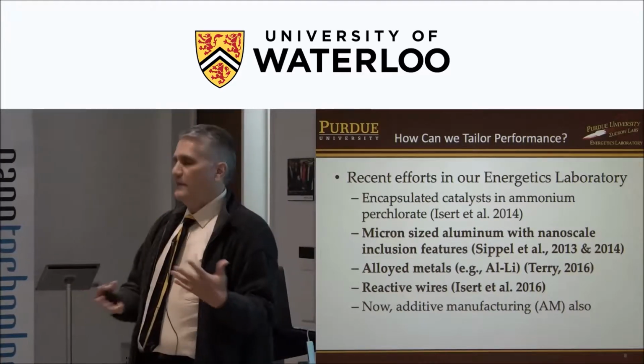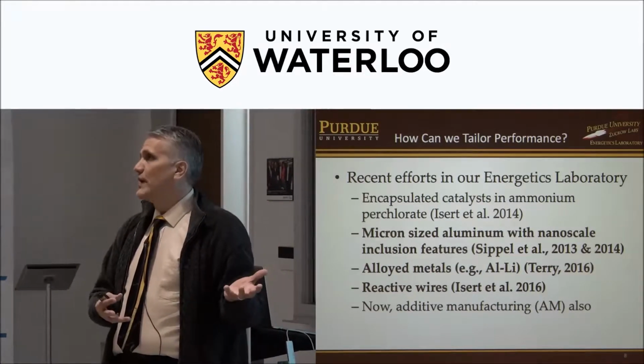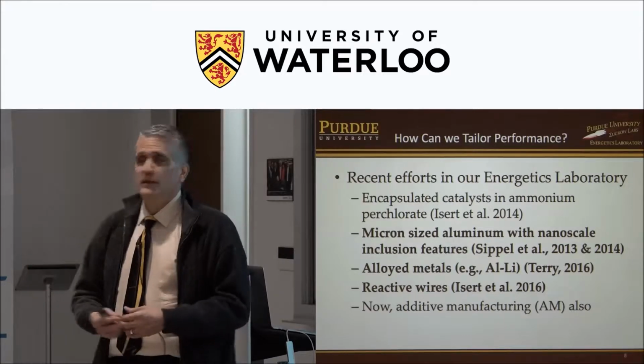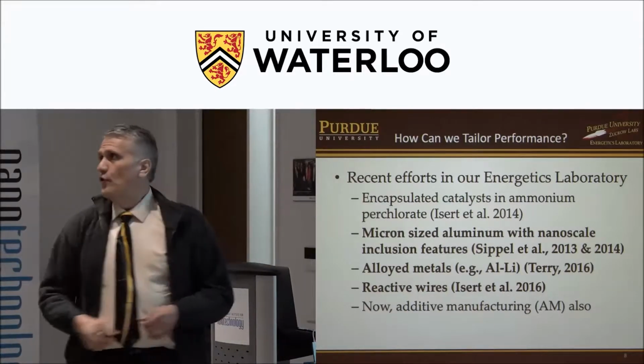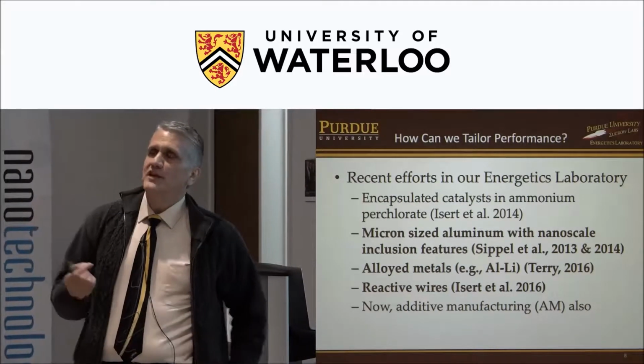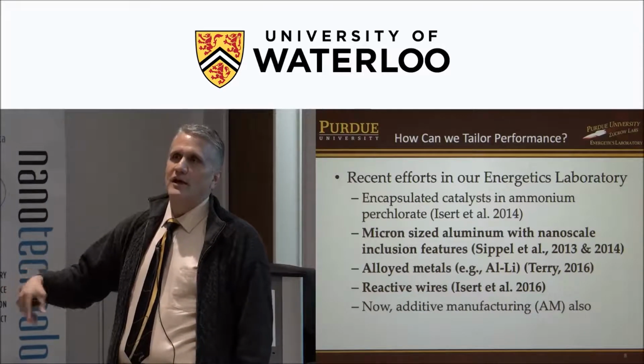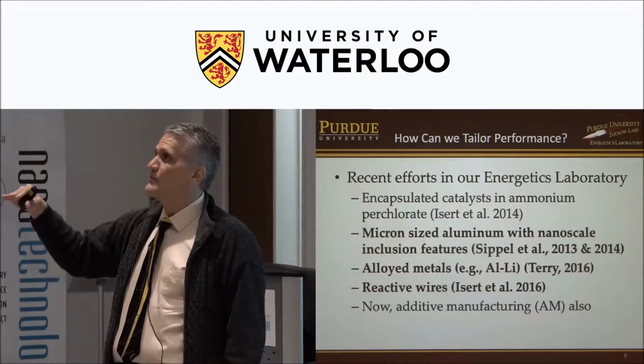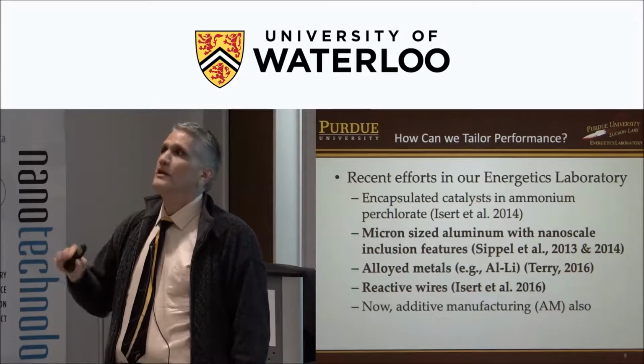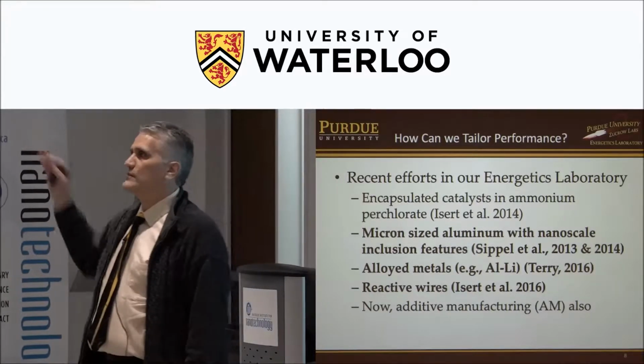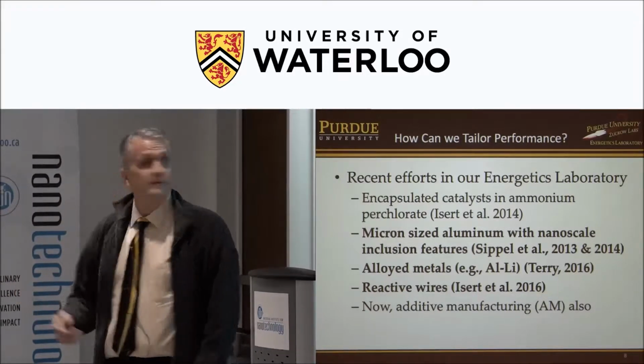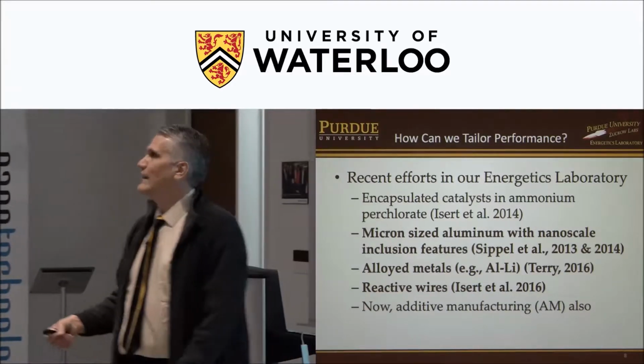We can apply just thermochemistry calculations and show that theoretically we would get better performance. Remember what I said, specific impulse improves if we have lower molecular weight or higher temperature. The temperature drops a little bit with aluminum lithium versus aluminum, but the molecular weight drops enough that the performance goes up. But just as interestingly, the lithium is hygroscopic.